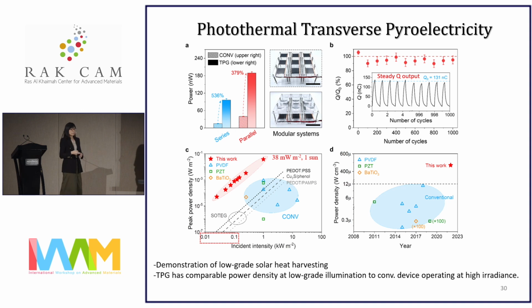In order to demonstrate the scalability, stability and practicality of the low-grade solar heat harvesting, we have designed a modular TPG system, as well as a conventional system of 3x3 units. The enhanced output of the TPG shows about 536% improvement in the series configuration, and 379% improvement in the parallel configuration. Besides that, the steady charge output in the 1,000 heating and cooling cycles shows that there are negligible current leakages, as well as electrostatics that are independent of the cycling.